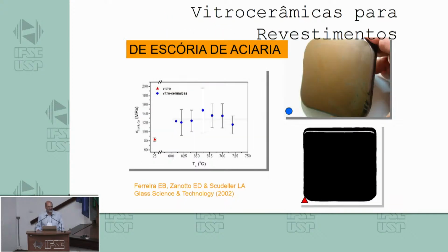This is one of our glass ceramics made by volumetric crystallization. It's in Portuguese, I'm sorry, but this is made from steelmaking slag that is wasted by the industry. And even today, they don't find much to do with this waste. And after so many years, Edgar, I'm very impressed finding this is still shining. The surface is not attacked by moisture. It's the same as on the day I prepared it in LaMaV, more than 20 years ago, maybe 30, no, between 25 and 30. Yeah, on Saturday I can show you this, okay? To those who have the luck to visit us.